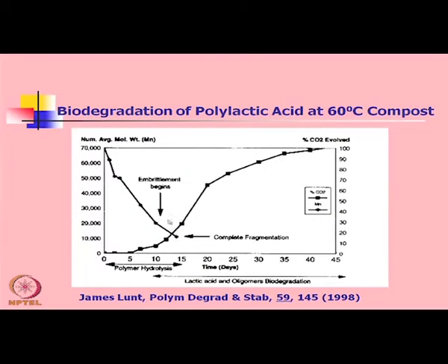This shows the decrease of molecular weight with time during degradation, as well as evolution of carbon dioxide due to biodegradation of the polymer. Now, here within 10 days time, embrittlement of the polymer to fragmentation starts, and ultimately between 10 to 15 days, after 15 days, it has been found that the polylactic acid